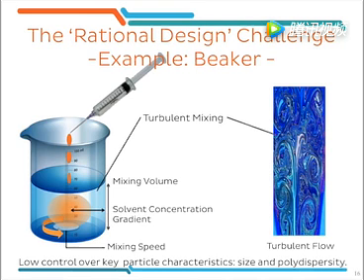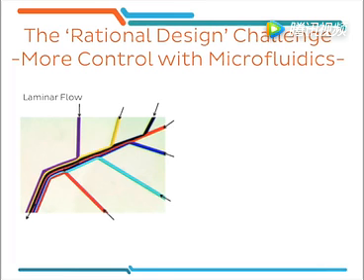So how can we get better at controlling this mixing and hence self-assembly process? This is where microfluidics comes into play. In microfluidics, we inject two miscible solutions, the ethanol solution with lipids and the buffer, into a sub-millimeter sized channel under laminar flow conditions. This means that the fluids will flow next to each other.